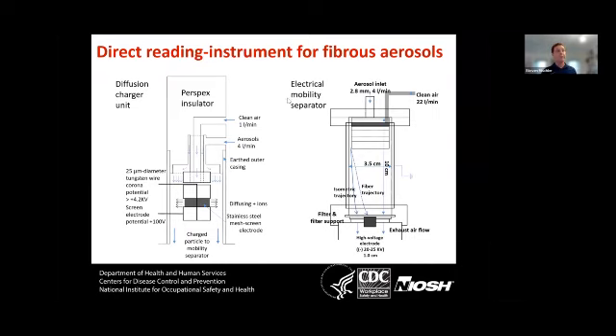We have an electrical mobility separator. The nice thing about using this for fibers is that fibers have the ability to collect much more charge than other spherical particles. And so we think we can charge these fibers and then use this electrical mobility separator to only collect fibers. You can see here that the isometric particles, or the less fibrous particles, will be impacted on the outer side of the filter, whereas the fibrous particles will move towards the center.